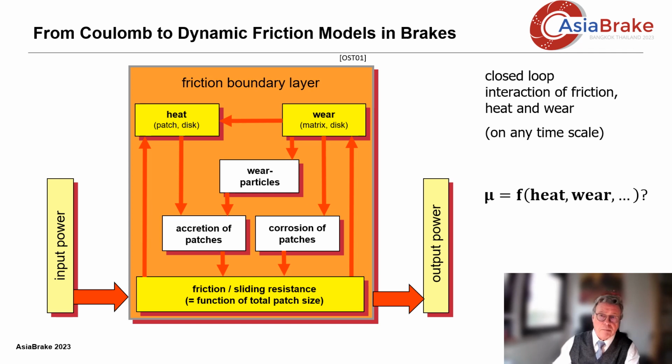Birth and death of these patches can be seen as part of a cycle process. The input power produces friction, the friction produces heat and wear, and the wear produces particles which, together with the heat, cause the buildup of patches. The wear itself limits the lifetime of these patches.